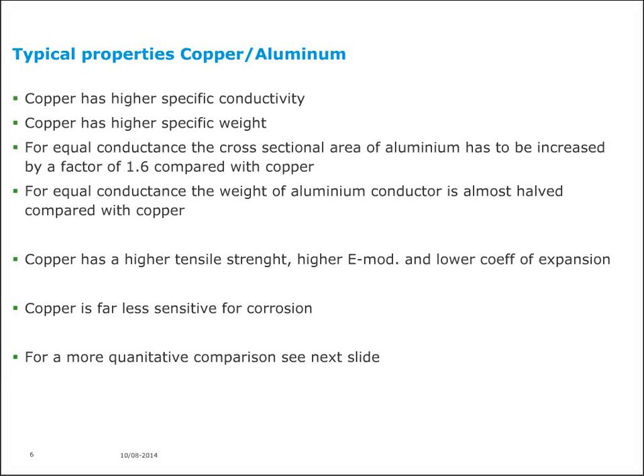Talking now about the typical properties of copper and aluminum. Copper has a higher specific conductivity. Copper also has a higher specific weight. For equal conductance, the cross-sectional area of aluminum has to be increased by a factor of 1.6 compared with copper. In other words, for the same resistance, aluminum conductor is larger than copper, has a bigger conductor radius. For equal conductance, the weight of aluminum conductor is almost half compared with copper. So for the same resistance, conductance, aluminum conductor is half of the weight of copper.